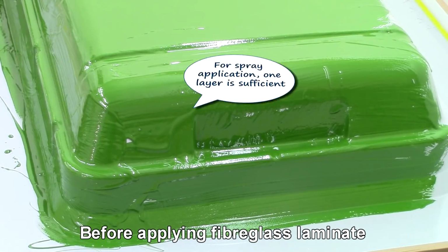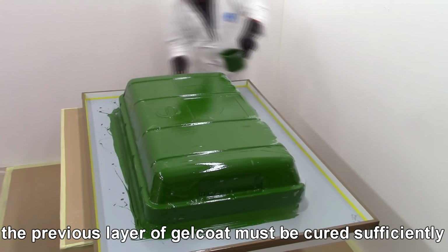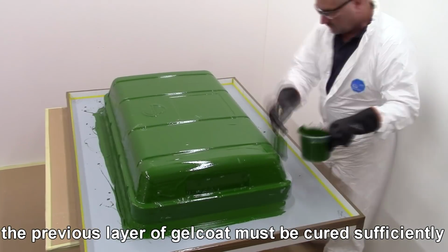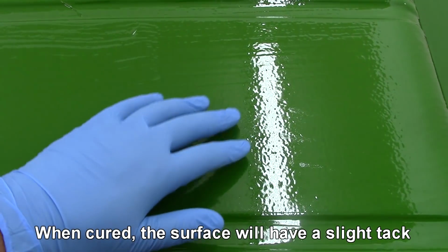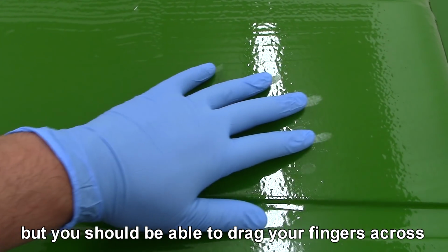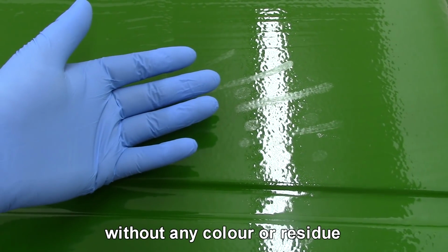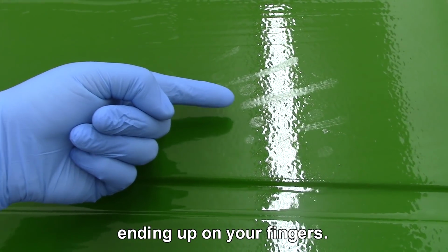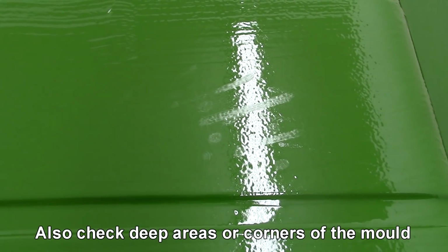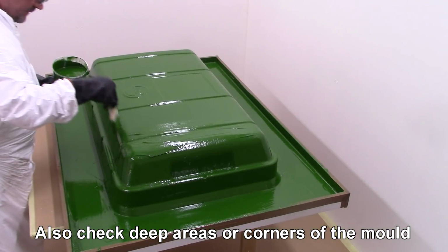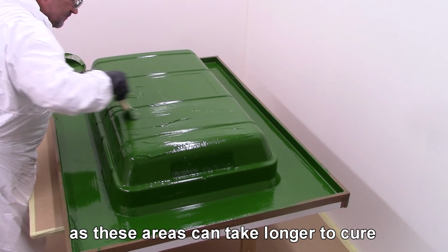Before applying fiberglass laminate, the previous layer of gel coat must be cured sufficiently. When cured, the surface will have a slight tack, but you should be able to drag your fingers across the surface without any colour or residue ending up on your fingers. Also check deep areas or corners of the mould, as these areas can take longer to cure.